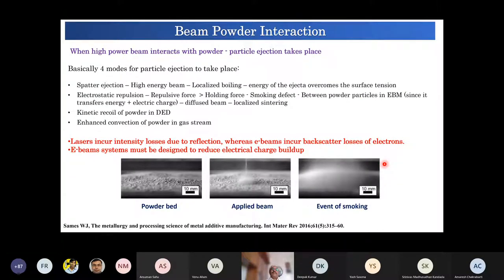Then comes beam powder interaction. Beam powder interaction depends on the kind of sources that we use, right? There are four types. One is spatter ejection, which is related to high energy beam, localized boiling, and the energy of the ejected particle overcoming the surface tension. In that case, spatter ejection takes place. Then electrostatic repulsion acts, particularly when e-beam processes are being used.